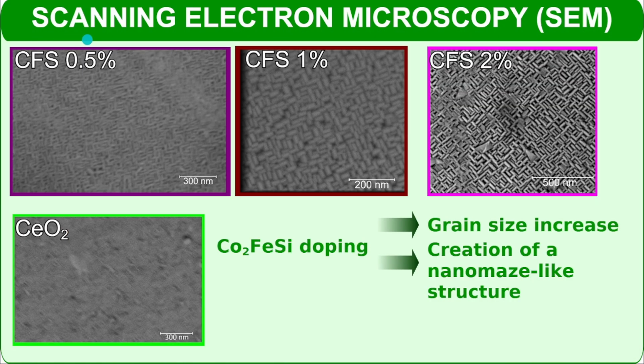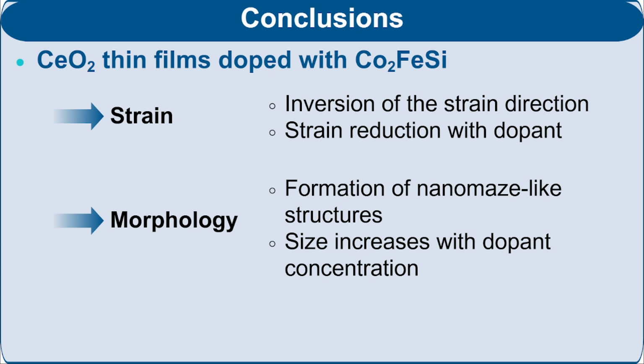When comparing the films side by side, we observed a clear increase in grain size along with the development of a distinct nanomaze-like structure, as we observed the inversion of strain in the films. In conclusion, we successfully inverted the strain in the CeO2 films and reduced it by doping them with Co2 iron silicon. Additionally, we observed the formation of a nanomaze-like structure which grew in size as the dopant concentration increased.